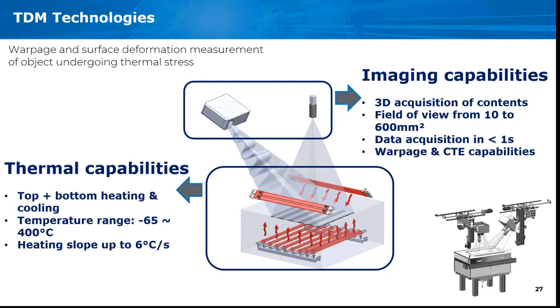The samples are being put into a chamber, which has some thermal capabilities. They are being heated up from the top and bottom with a slope up to 6 degrees C per second and a temperature range from -65 to 400 degrees C. So the point is to be able to simulate any reflow, SMT, or other types, and to check the warpage at different temperatures.